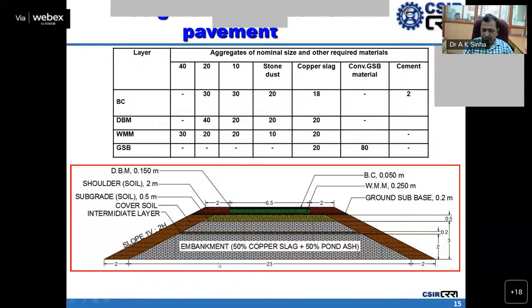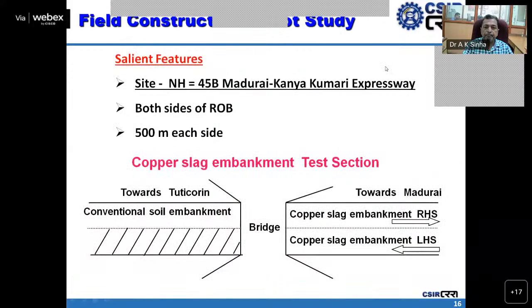A typical cross-section was designed for field construction, where the embankment was constructed using 50% copper slag and 50% pond ash. And this is the pictorial view of the designed cross-section. And based on that, a pilot study was carried out, and this is the salient feature of the project. The project was constructed at Tuticorin, Tamil Nadu, along National Highway 45B, Madurai to Kanyakumari Expressway. At the ROB, on the right side, copper slag was used as embankment material, and on the left of the ROB, the embankment was constructed using conventional soil materials. Both approaches, 500 meters each side, were used for the experimental test section.